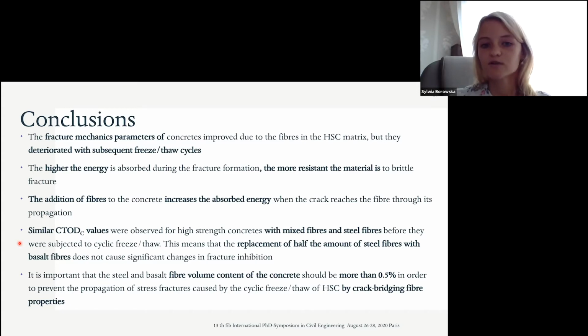The presence of fibers in high-strength concrete significantly increases their absorbed energy. Steel and basalt fibers in concrete can withstand tensile strength, reducing the formation of cracks and limiting stress concentration at the tip of microcracks, preventing them from spreading, thus eliminating the formation of combined cracks. However, special care must be taken to ensure that the fibers are correctly distributed in the concrete mix, and a proportionally higher number of fibers must be used to prevent the propagation of future fracture formation that occurs with the subsequent freeze-thaw cycles.